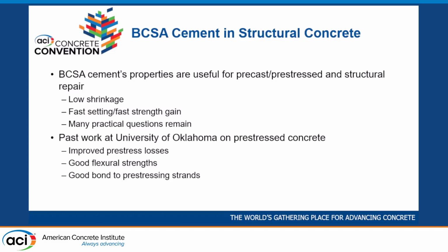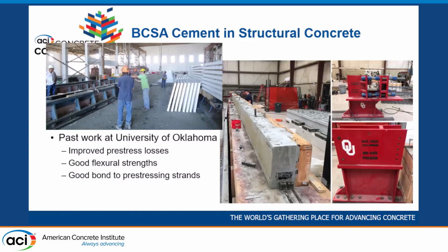My introduction to this was when I was a graduate student at the University of Oklahoma, and I was fortunate to help out with a couple projects looking at pre-stressed concrete using BCSA cement. On the left, we partnered with a local precaster and made structural scale precast concrete elements that were pre-stressed with BCSA cement. It was a feasibility study. On the right, we did more of a lab study, looking at bond between strand and concrete and flexural strengths a little bit. And we found that the cement had improved pre-stress losses compared to Portland cement because of its low shrinkage primarily, good flexural strengths, and good bond with strands. So this encouraged me to continue down this path of looking at this cement for structural applications.